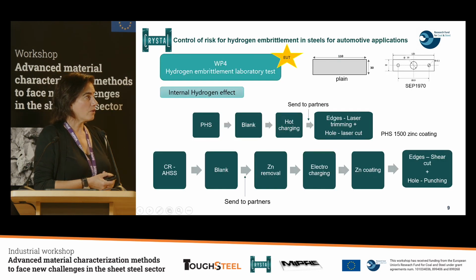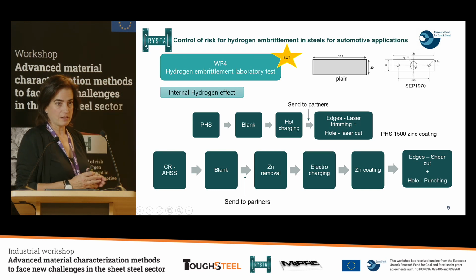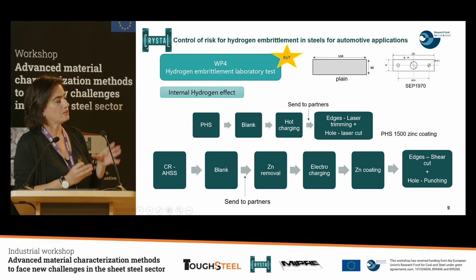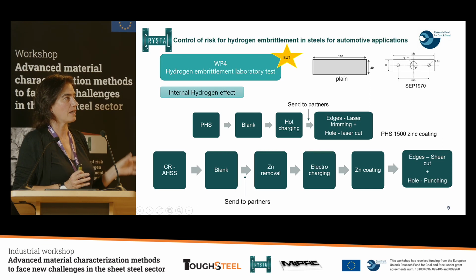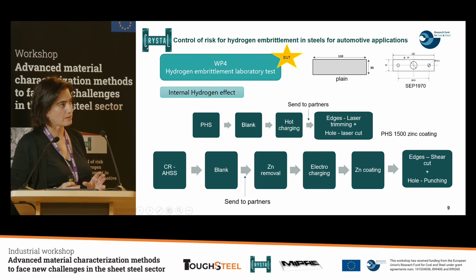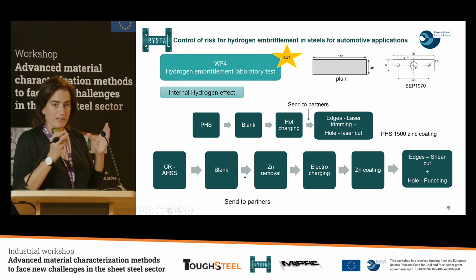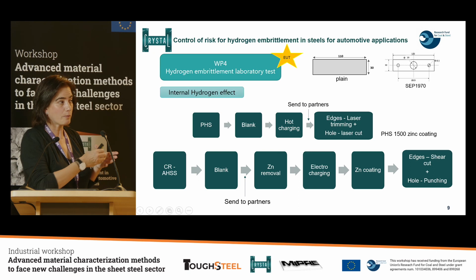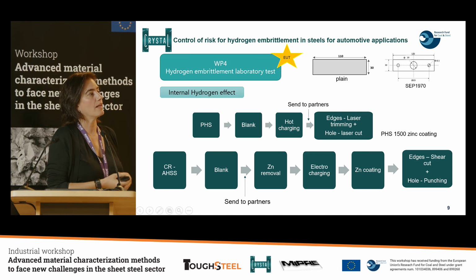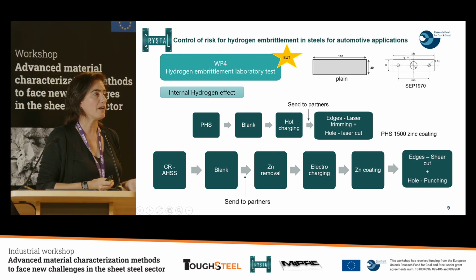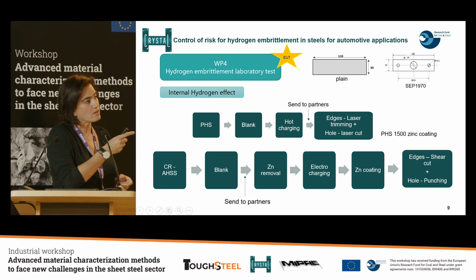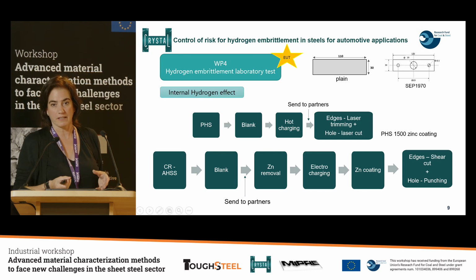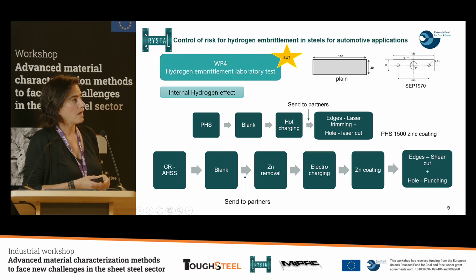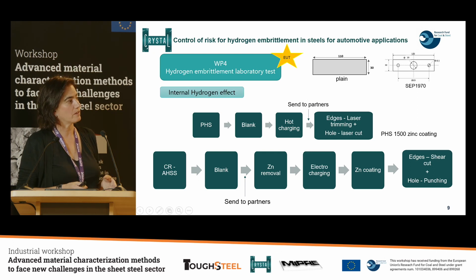Here is work package 4, where we perform all the laboratory tests. As I said before, we divided this work package into big tasks to measure the internal hydrogen effect and the external hydrogen effect. And we had several meetings at the beginning of the project to decide which was the best sample geometry to perform all the tests. In this case, we selected a plain sample to perform the U-bend and the 4-point bending test, and a SEP1970 for all the tests, except the cracking resistance. And also we had several meetings to define how the samples had to be prepared.